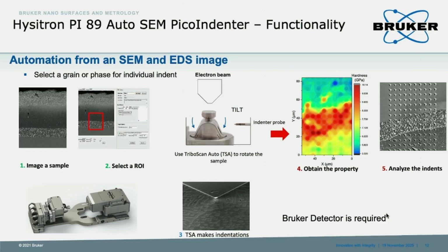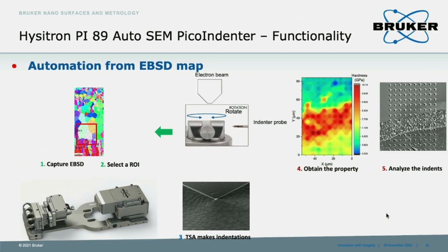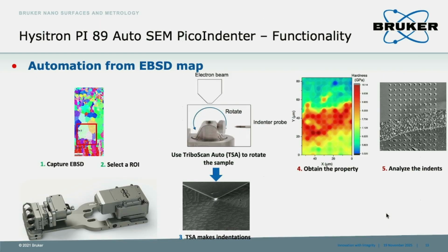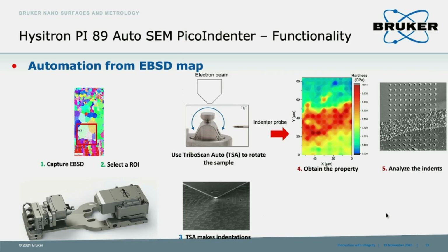Yeah, it's quite robust. And EBSD is the same. For EBSD, we need to use the rotating stage. Just turn 90 degrees and go back to the electron beam to see the post-test image. This is very powerful. If you capture the EBSD image first, then our system is calibrated with the SEM. Then you can get the post-test topography image, the mechanical properties mapping, and also EBSD in one chamber. And you don't need to vent the SEM to take the sample out. You complete the testing here.